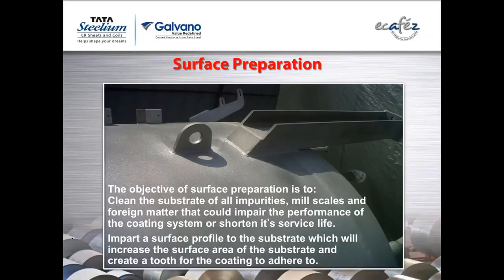So the objective of this surface preparation is to clean the surface of all impurities, mill scales, sometimes rust, foreign matter that could impair the performance of the coating system and shorten its service life. So we have to remove those, clean the surface, and then impart a surface profile to the substrate, which will increase the surface area of the substrate and create a tooth for the coating to adhere. So you'll get better adhesion when you have more surface area created, and the surface profile is good.